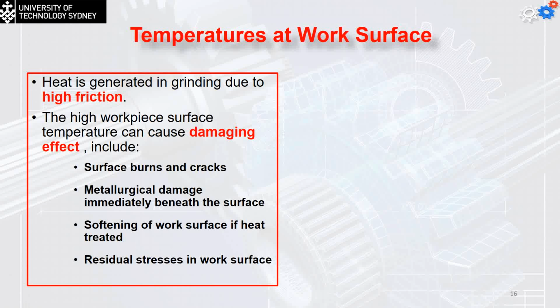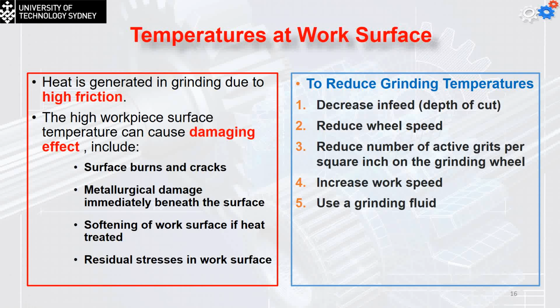Now, to get rid of these effects, we can do the following. First, we can decrease the infeed, the depth of cut, so instead of doing the cutting, we can do the plowing. Reduce the wheel speed, so the speed of the friction is going to be less. Reduce the number of active grits per square inch of the grinding wheel, so we go a little bit coarser than denser. And increase the work speed, the oscillating velocity, and use grinding fluid, which is something like the cutting fluid, which does the cooling in the machining process.